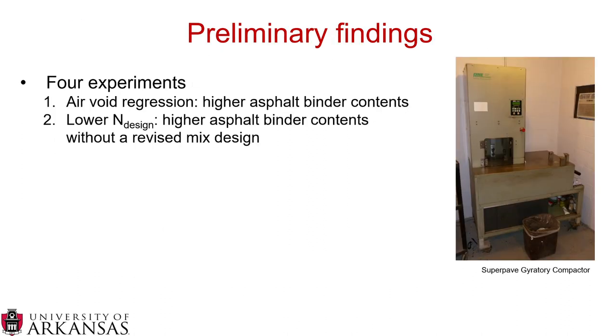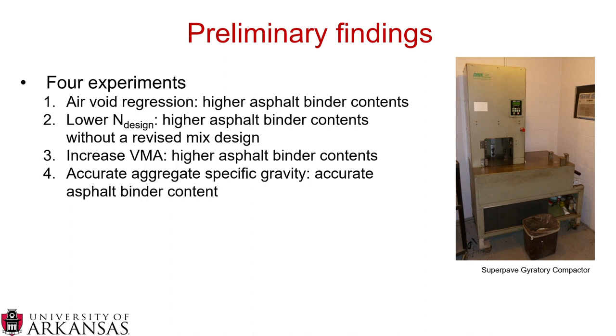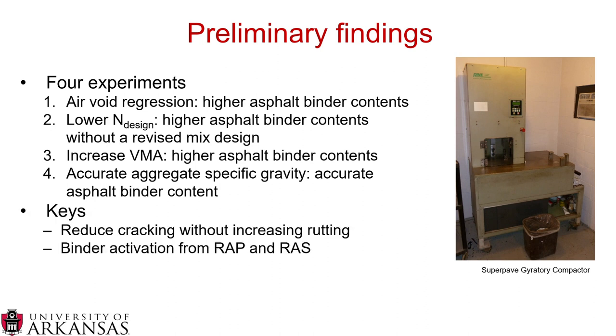So some preliminary findings from Tran's study were they performed four experiments. They did an air voids regression, and they found that higher asphalt binder contents were helpful. They lowered the Ndesign, and they found that higher asphalt binder contents occurred without revising the mix design. That's a key caveat. They found you could increase VMA, and that would result in higher asphalt binder contents. And they also emphasized the need for accurate aggregate specific gravities, because that will give you a more accurate asphalt binder content. And that goes back to the effective asphalt binder.